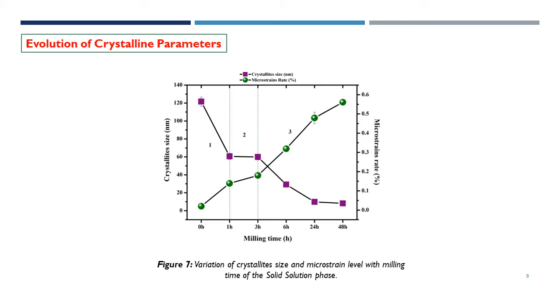On the other hand, the variation of the microstrain rate with milling time indicates that mechanical alloying causes significant lattice straining. The incorporation of both cobalt and nickel into the iron matrix results in a significant increase in the microstrain rate, as it is expected. During the deformation process, it rapidly rises and reaches a maximum for longer milling time.